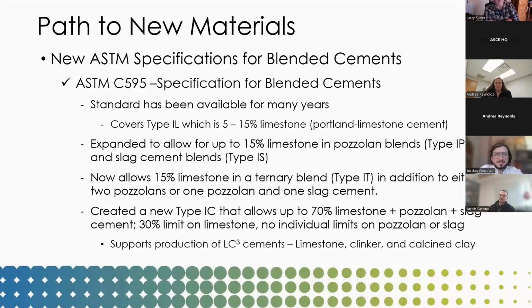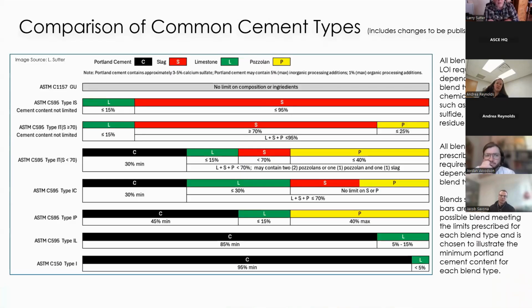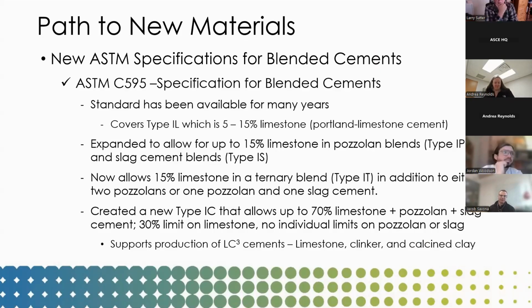And we've also allowed 15% limestone into a ternary blend. And that limestone does not count as a blending component. So it's 15% limestone plus either two pozzolans or a pozzolan and slag. These are important changes. These are materials that are in the marketplace right now today. ITs, IPs, ISs are in the marketplace. Please go back one slide. And they're in the marketplace today and they're being used. And so this is going to be a major change that's coming our way.